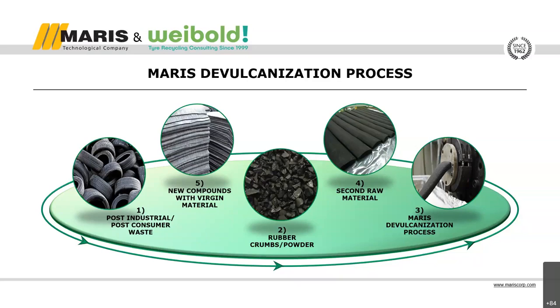Rubber crumb powder feeds the twin screw extruder for point 3. The picture of point 3 shows the devulcanized material exiting from the die in a strip form that is typical for this process. As I said before, the process is continuous, so we can collect the material continuously. See the picture in point 4. As I'll explain later in more detail, our second raw material can be used with virgin rubber to create a new compound. Now, for the next slide, I'm going to give you the theory and the main features of our process.